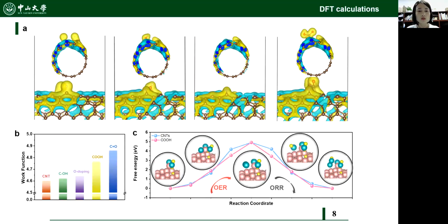Density functional theory calculations were also performed to unveil how electron density modulation affects the catalytic performance of CNTs at the atomic level. The charge density distribution clearly revealed the strong interaction between the oxygen functional groups and intrinsic carbon atoms, inducing remarkable electron accumulation on oxygen atoms and obvious electron depletion on carbon atoms. This result is also proved by Bader charge analysis.